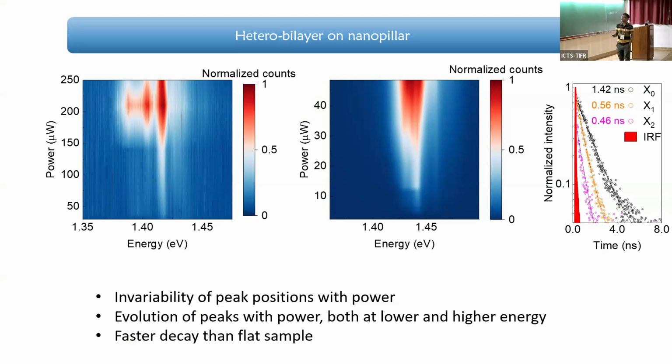Another thing is that the lifetimes are much faster. This is nowhere close to 100 nanoseconds or so. This is something like 1 nanosecond or even less. There are even faster components over here also, maybe 100 picoseconds or something. Which also makes sense because there are these lower energy states available here, so it's going to a lot of non-radiative processes.